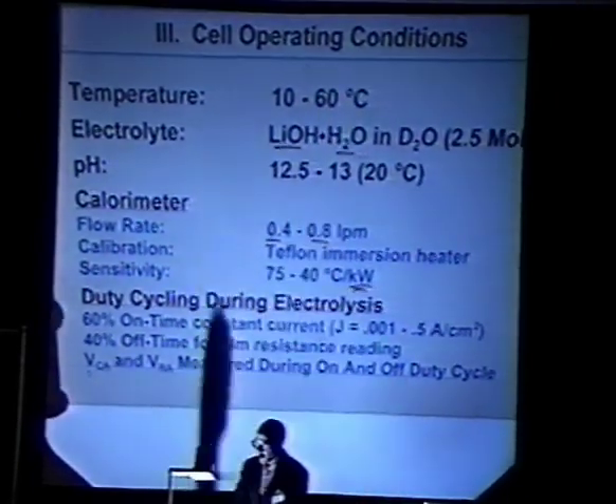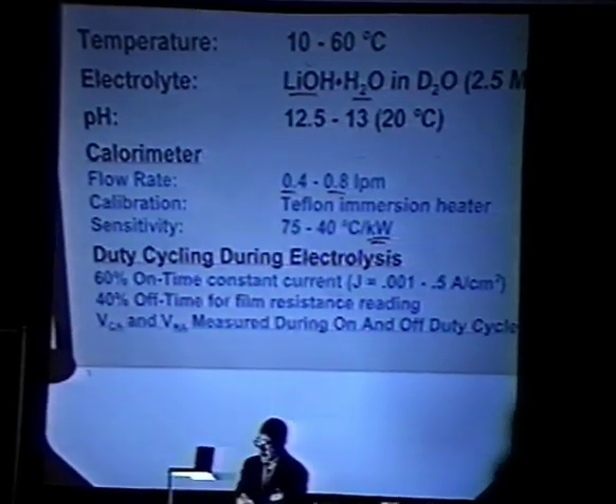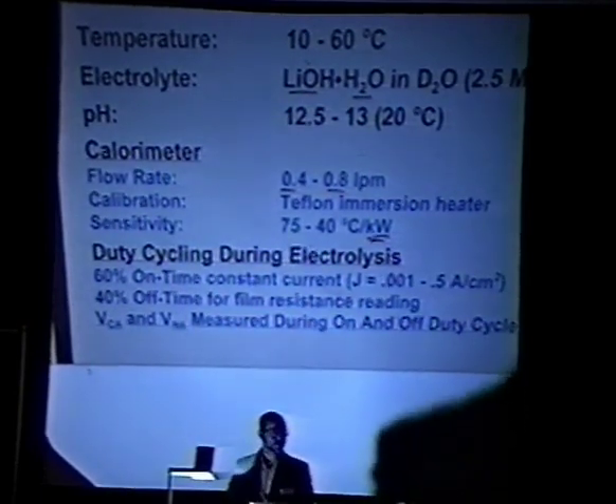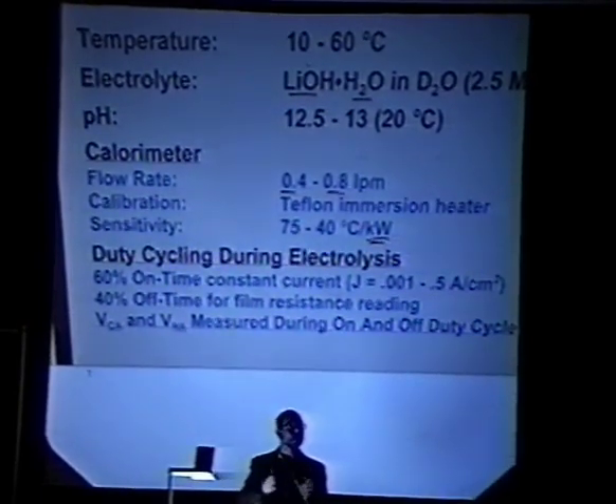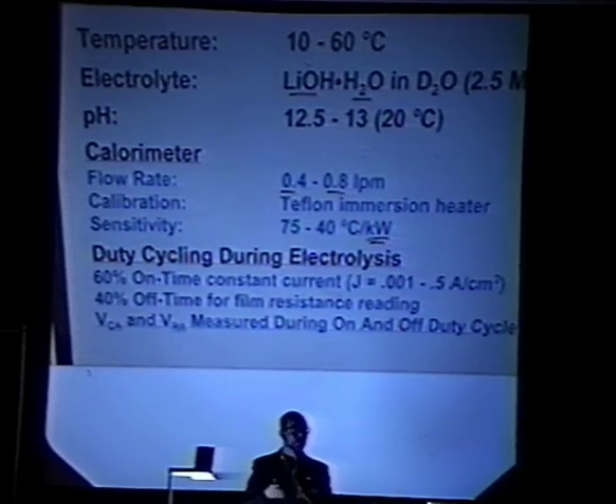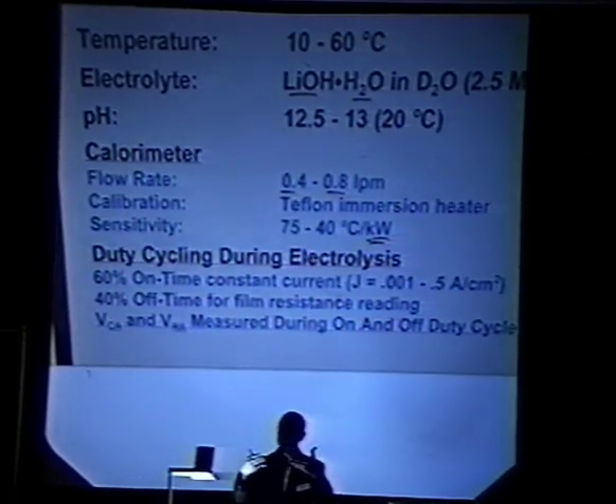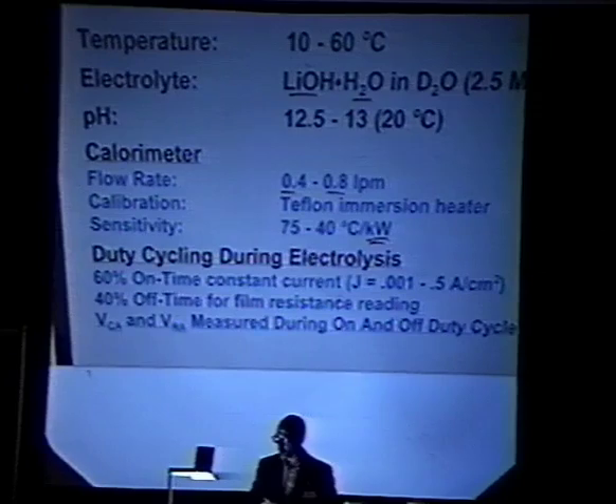And the way it's operated, the duty cycle, typically 60%, every 30 seconds, 60% of that time, I have the current going when I'm electrolyzing. And then it's turned off for 40% of the time where I go through and resample all the voltages between the reference and the cathode, and also between the anode and the reference electrodes, and then do the 4-wire resistance measurements. So I kind of have an off-time measurements and an on-time measurements. And that happens both with or without the electrolysis current turned on.